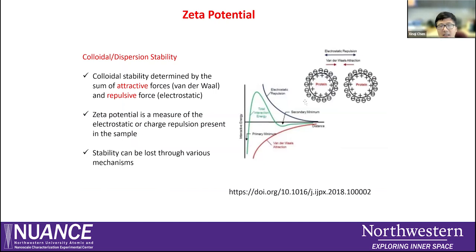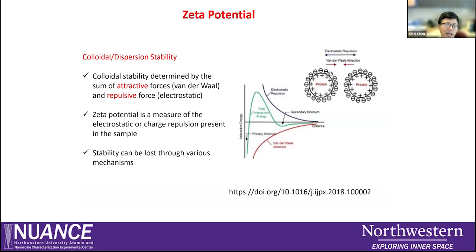Now let's move to the second topic: zeta potential. Zeta potential relates to the stability of colloids. In a suspension, particles experience two forces: an attractive force (van der Waals force) and a repulsive force (electrostatic charge). All particles of the same material carry the same surface charge and are surrounded by an opposite charge layer, causing them to repel each other. Zeta potential measures the strength of this repulsion and indicates whether your suspension is stable or not.